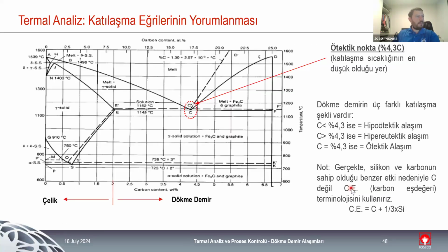And again, we have the phase diagram, and I just want to point out that we are always talking about carbon content, but in reality, and as we already discussed and you are all aware, we have a lot of other elements that are present in the melt, especially silicon. After carbon and iron, it is the element that we have in higher amount in the melt. So for the study of the phase diagram and thermal analysis, we change the carbon content for what is called the carbon equivalent. That is a mix of carbon plus 1/3 of the silicon content.